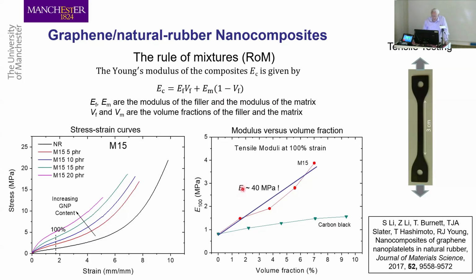However, the slope of this line says that the graphene has a modulus of 40 megapascals. Okay, well, that's not very much. We know the graphene's got a modulus of 1,000 gigapascals, so 40 megapascals is not a great deal. Why is that? Well, I don't know.